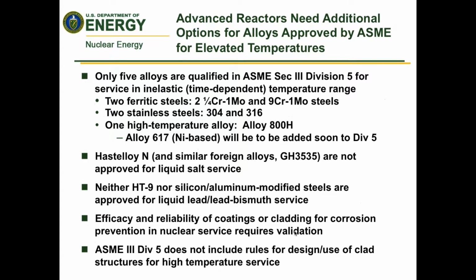Now, it's important from the get-go to realize that there are only 5 alloys that are currently contained within ASME Section 3 Division 5 rules for high temperature reactor component construction that are allowed for this high temperature service: the 2 ferritic steels, 2 1/4 chrome and 9 chrome, 2 stainless steels, 304 and 316, and the 1 high temperature alloy 800H. Alloy 617, high temperature nickel alloy, will be added almost surely within about 3 years, so that will be 6, but still, that's it.